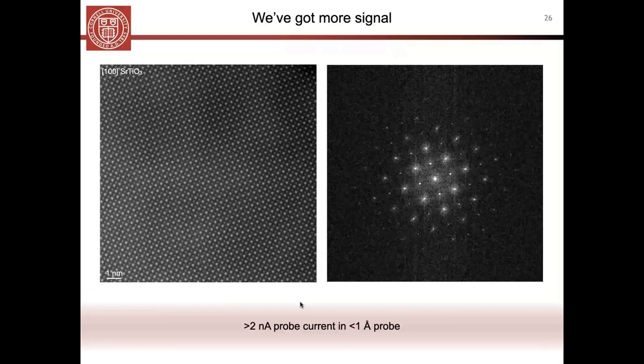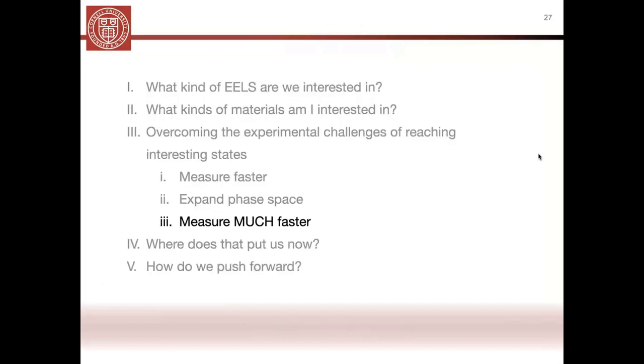We typically work with things like 100 picoamps for these kinds of robust materials. And anyone who works on biological specimens or soft matter will, of course, be completely blown away by the idea of putting 2 nanoamps of current onto your sample. But looking at the information transfer from this image, we have information transfer out to 64 picometers. So really we are packing a punch with this STEM probe. That is how we're going to put more signal into our sample in the same amount of time. What that allows us to do is not just improve the signal, but we can now signal limit ourselves and measure much, much faster.